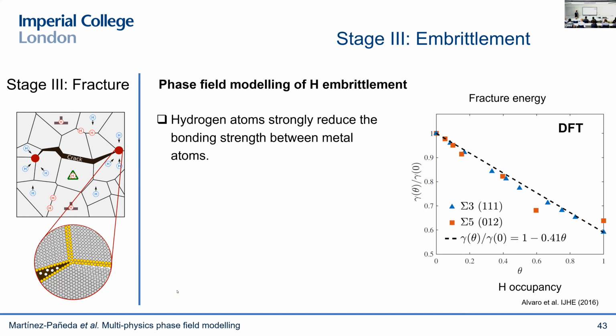You need to think of the problem across multiple scales. The first one is that if you do atomistic calculations, DFT or molecular dynamics, what you see is that the surface energy or the fracture energy is very sensitive to the hydrogen occupancy. You can see here, if my interface, let's say a grain boundary, is full of hydrogen, the coverage is equal to 1, then I get a 40% reduction in fracture energy. So this is the first ingredient. Hydrogen is going to make my grain boundaries much weaker.